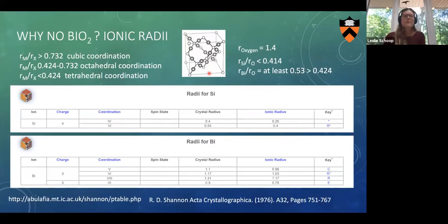But let's do it with bismuth. The first problem we run into is that it doesn't exist in charge +4, and that's related to the P electron problems that I mentioned before. However, let's not worry about this right now. Let's look if we find it in 4-fold coordination. Oops, it's another problem. It's not even tabulated to exist in a 4-fold coordination. But to be fair, let's just pick the smallest number listed. This is all the measured radii for bismuth in the different materials. If you take the smallest one, 0.76, and divide it by 1.4, we get 0.53, which is way too large to fit in a tetrahedron. So it's just not possible to shove a bismuth cation into an oxygen tetrahedron for simple size considerations.